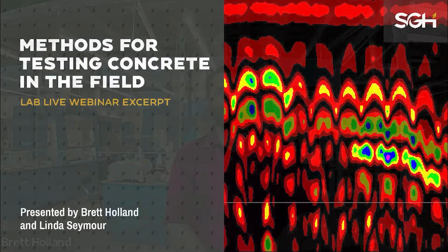When you go and do an investigation, you typically start with condition assessment, right? This might be a visual survey, localized sounding, or crack mapping, with the idea of trying to get an overall feel for what's happening. Depending on what you find, you then can determine what, if any, further evaluation is needed. These additional investigation methods could be things like non-destructive testing techniques, might be semi-destructive with small core samples, or it could be invasive, removal of large samples or openings in the structure itself.